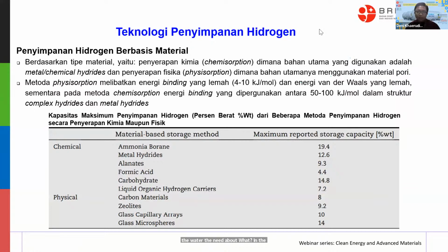Okay, for the storing of the material base, as mentioned before, this is the reported storage capacity. For the chemical, the weight of hydrogen that can be stored is higher compared with the physical one, like ammonia borane or even ammonia, considered high in the hydrogen that can be stored, and metal hydride, also alanate, formic acid, some formate, carbohydrate, and LOHC for 7.2. For the physical itself, the highest is the microsphere glass and capillary glass. But this is rather difficult.